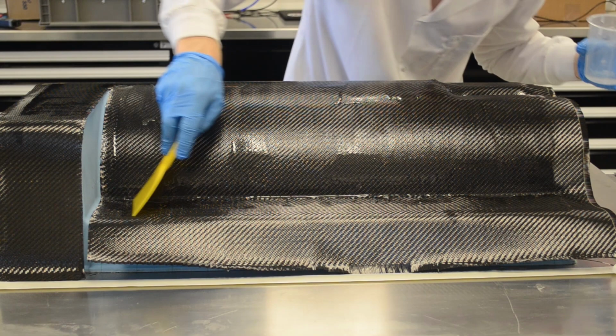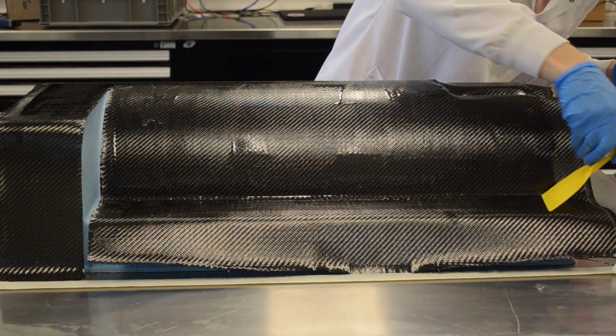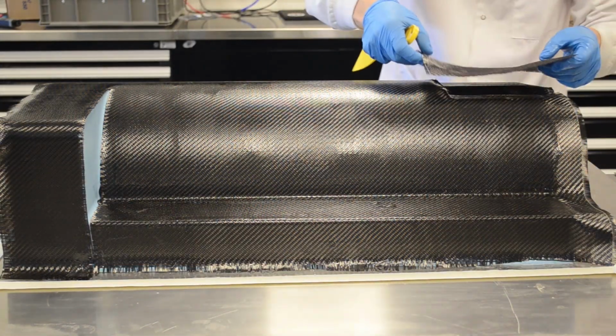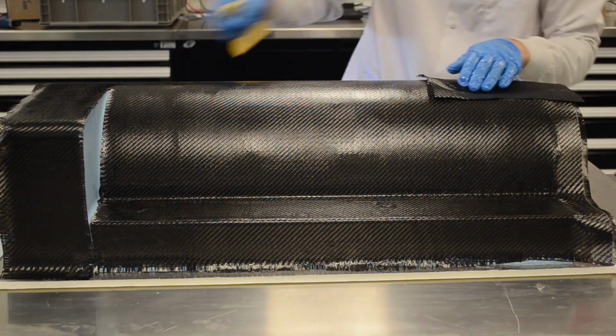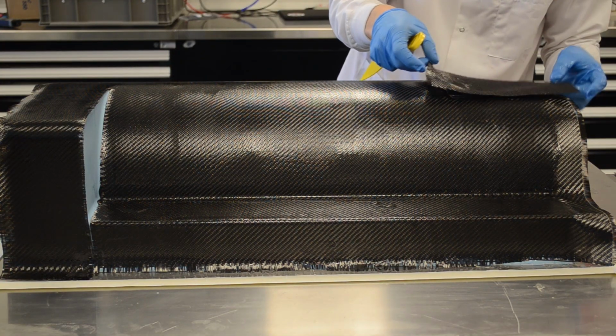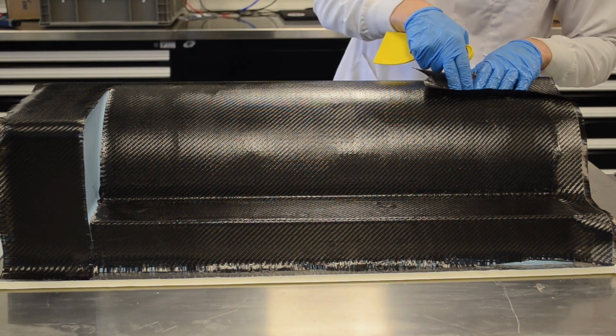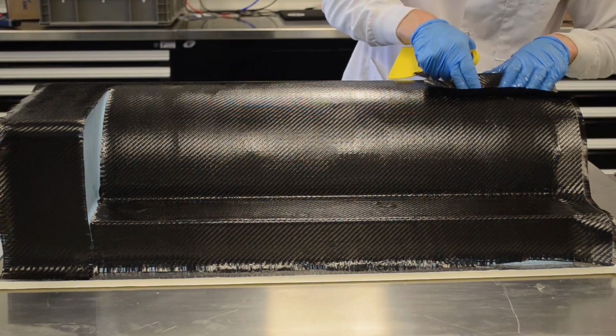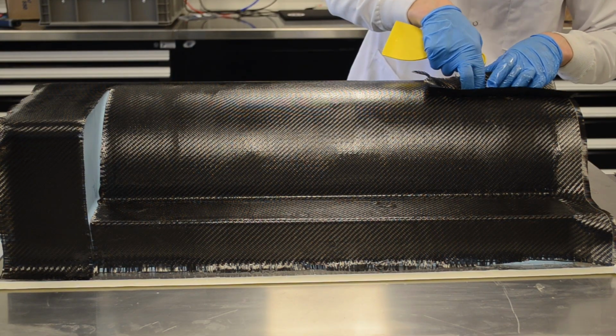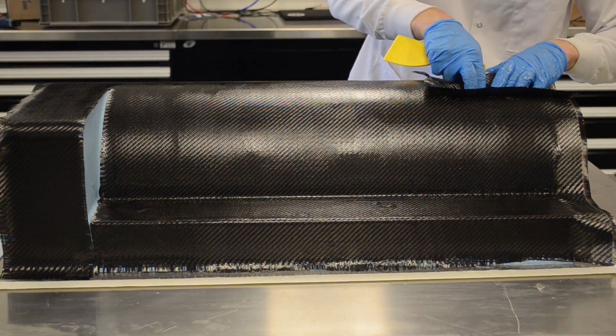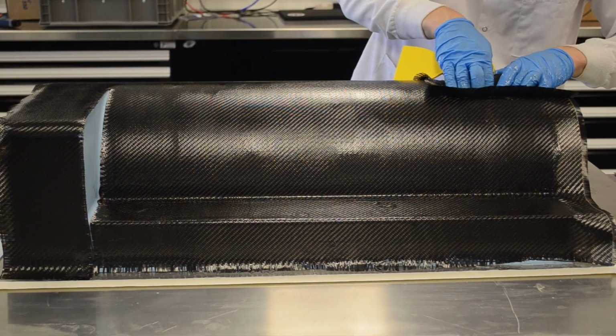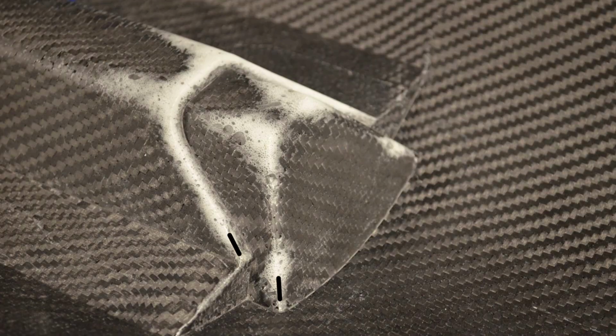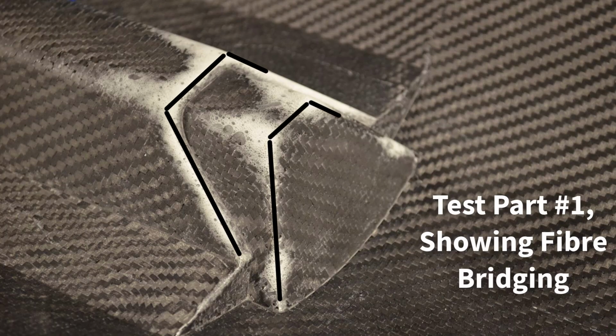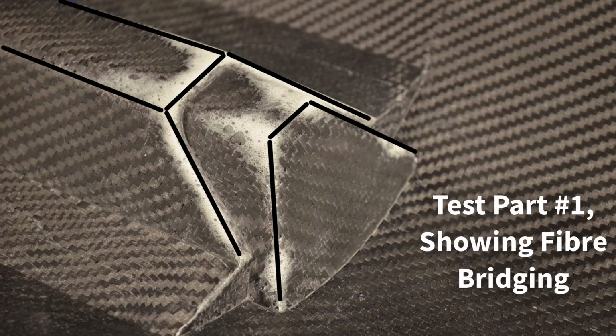For our third part, we will use a resin with a working time of 4 hours. We will also cut our fabric slightly differently around the areas with tight inside corners, cutting a slit in the fabric, also known as a dart, and adding an additional piece of fabric to cover exposed areas. The smaller fabric piece is easier to position into tight geometry without bridging. Alternatively, or in conjunction with smaller pieces of fabric, individual tows of fibers could be placed inside corners to ensure that they contain fiber and not just resin and air.